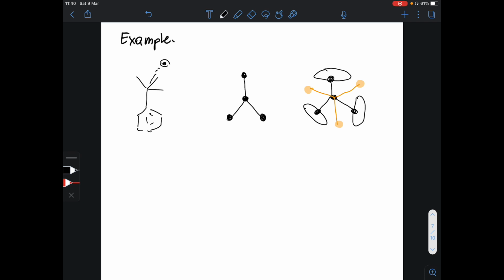The idea of a part is that all atoms that you have in your molecule are in so-called part 0, and they make bonds with each other, based on their distance. If we put something into part 1, let's say this marked in black, atoms from part 1 will create bonds to atoms from part 0.